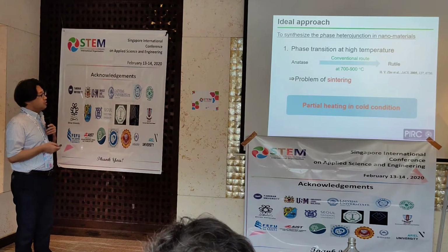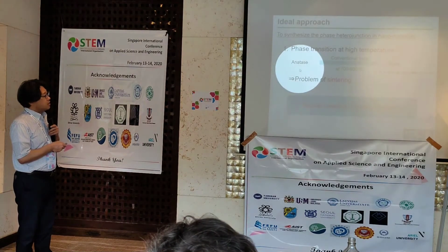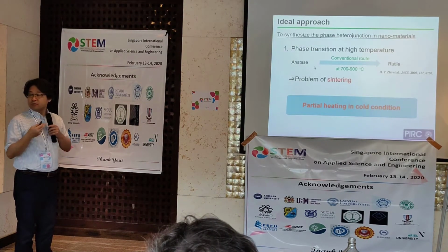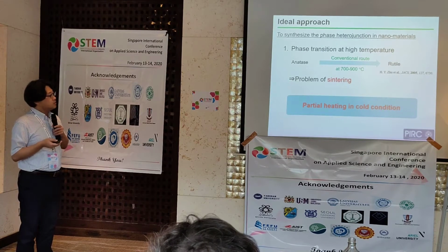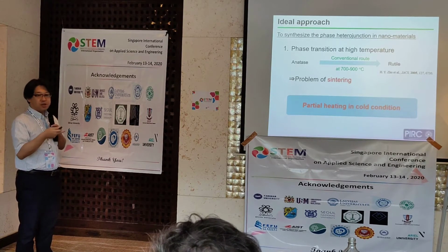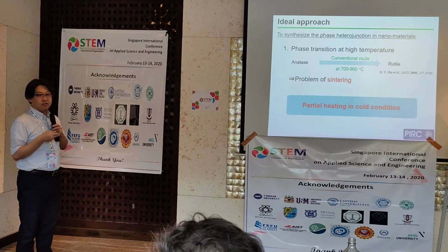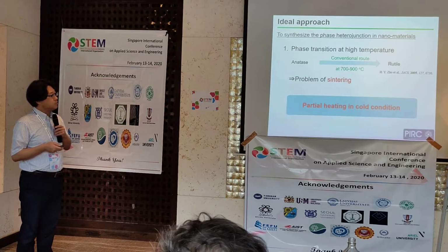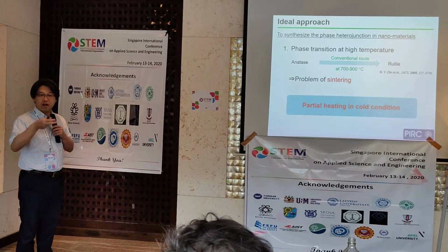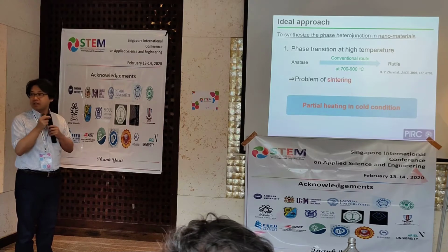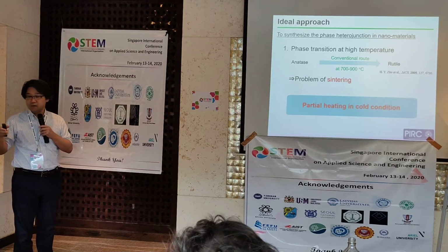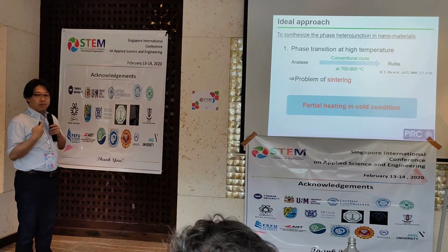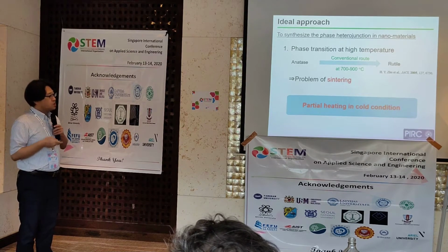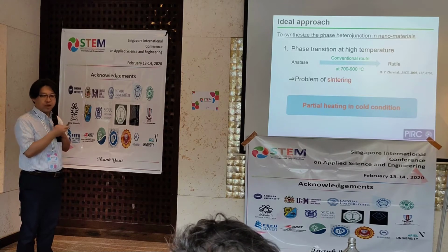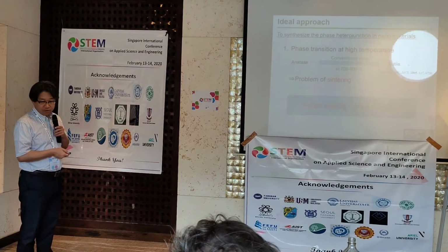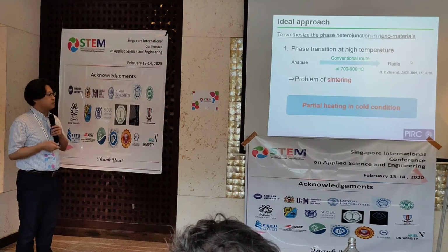because generally the starting material, anatase, transits to another crystal phase. In that case, the conventional route is a high temperature treatment at around 700 degrees. But the problem is sintering at a high temperature. Nanomaterial of titanium dioxide sinters at high temperature. So our strategy is partial heating in cold condition to make another crystal phase, brookite, and heterojunction materials.